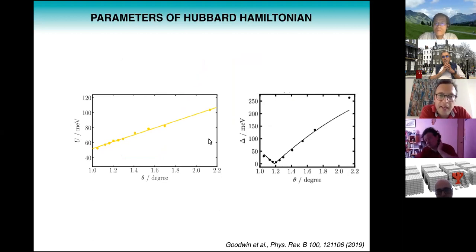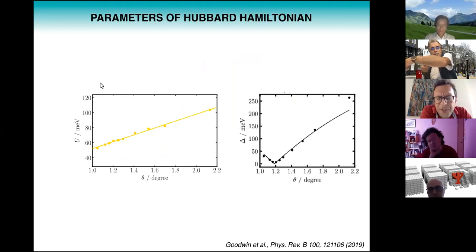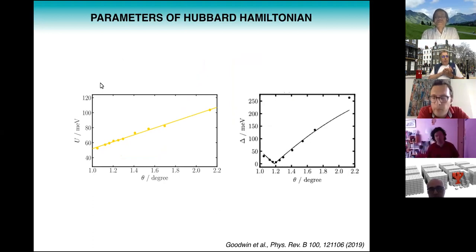Here on the left-hand side, I'm showing you the value of the Hubbard interaction, the on-site U, as a function of twist angle. I think we've assumed a background dielectric of 4 or 5 here to say that the twisted bilayer graphene is sandwiched by hexagonal boron nitride slabs. What you see is that the Hubbard parameter is on the order of 60 to 100 meV, and it becomes smaller as the twist angle decreases. That's just a reflection of the fact that the Wannier functions also scale with the size of the moiré unit cell, so they become more and more delocalized as the unit cell grows, and that leads to a reduction of U.